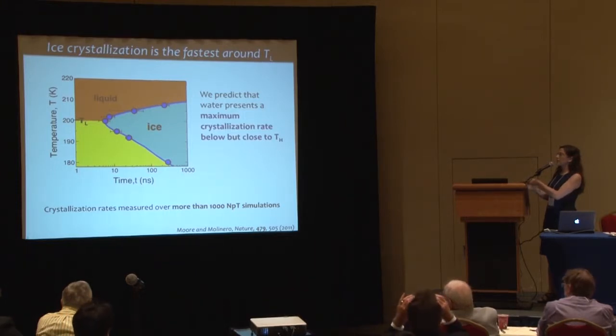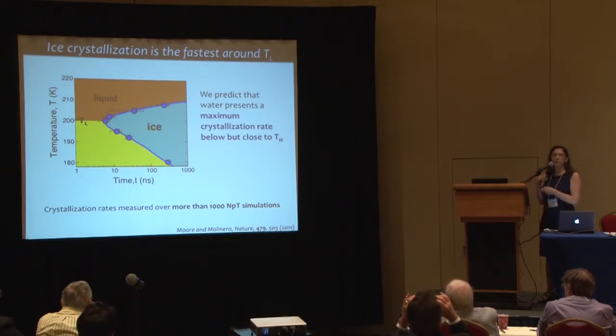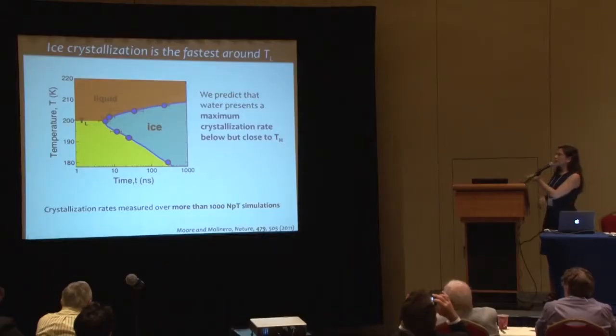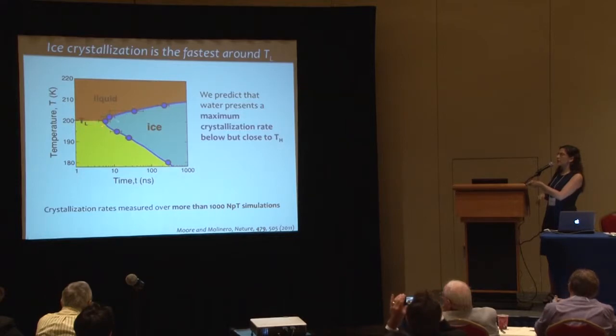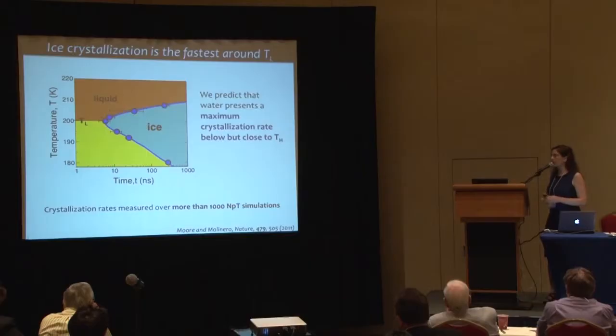The TTT diagram shows temperature vs. time: if you wait at each temperature long enough, you reach the crystallization time — inside the blue domain, ice forms. If you cool fast enough to pass through the nose without staying 10 nanoseconds, you can avoid crystallization. But even in that case, the glass already has crystallites and the criss-cross structure intermediate between liquid and ice.